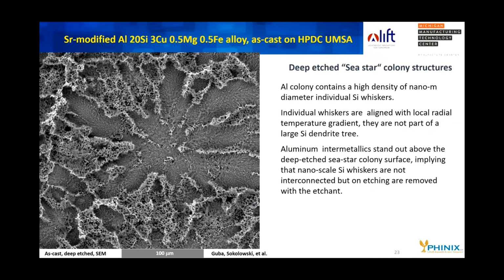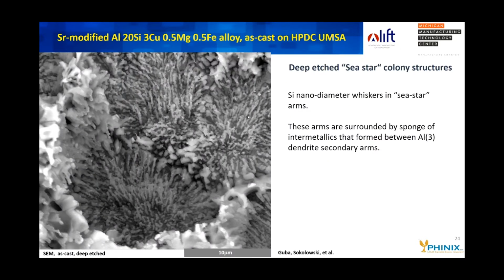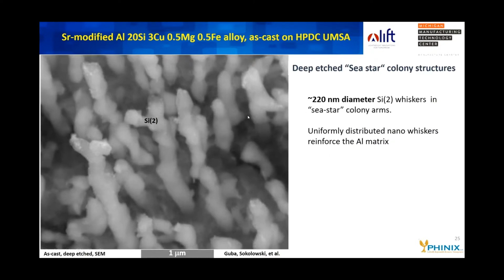This is at higher magnification, showing one of those sea star colonies, and you can see here the inside of the dendrite arm, and now you can see whiskers that are there. The interesting part is that they're etched down, and that implies that the whiskers are not interconnected dendrites, but individual whiskers which are etched out and removed with the acid etchant. So this is a higher picture of the nanoscale whiskers inside of the arm and the copper intermetallics at the cell boundaries.